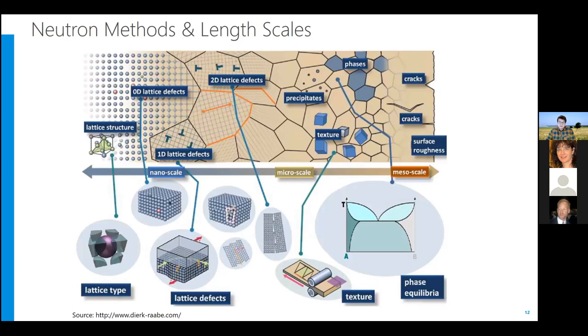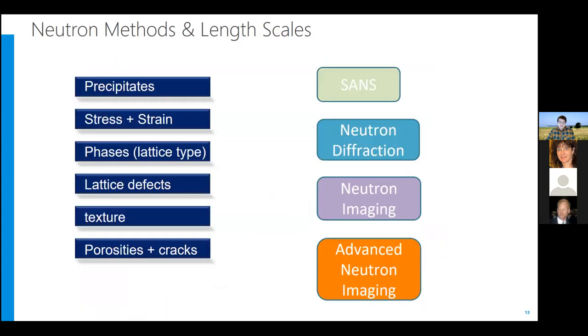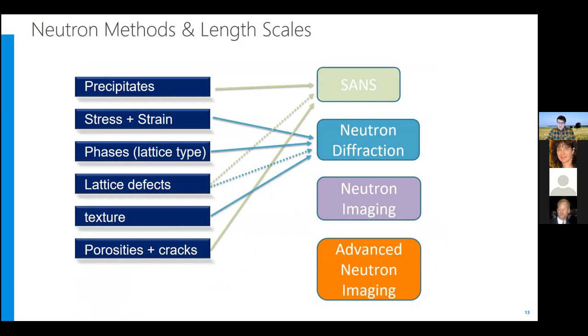Neutron methods, as you have seen on the previous slide, can access all of these length scales. So as such, you can, for example, use small angle neutron scattering to study precipitates, certain porosities, and crack sizes, or diffraction to study internal stresses, crystalline phases, and texture.